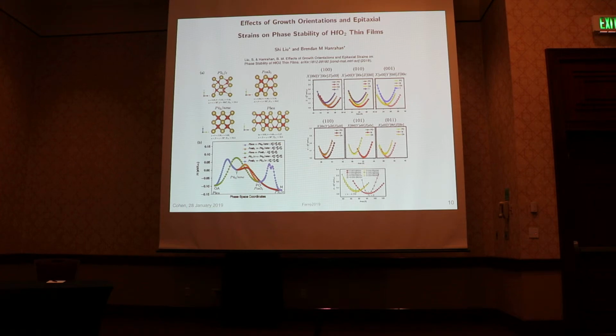So they look very similar when you look at where the atoms are. This is the nonpolar or antiferroelectric orthorhombic phase, and this is the polar one. And you can see this bit here fits over here. So it's really just a doubled cell. It's like a zone boundary instability that gives you this PBCA structure. But nevertheless, even though it looks like it should be very simple to distort one into the other, at least what he found in this paper is quite a large energy barrier between them.